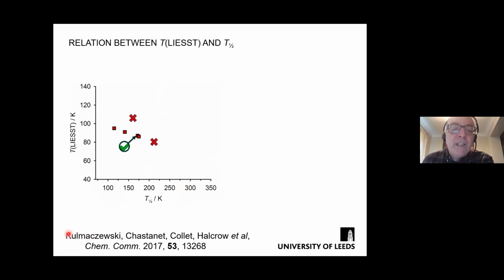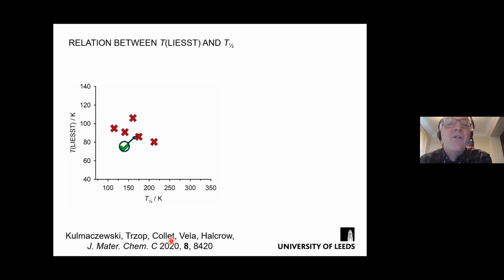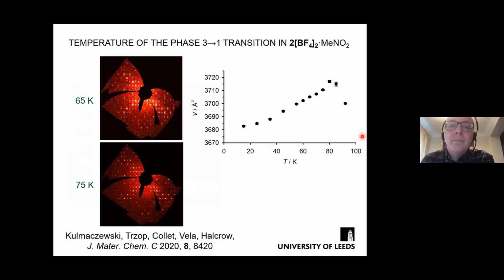But then after publishing this paper, the Royal Society of Chemistry gave us a grant which paid for more helium so we could do more measurements. So 2 years later, we measured the rest of these compounds. And this compound does not do the phase changes, and neither does this one, and neither does this one. So this material is the only compound out of 6 that does those phase changes. So what is going on?